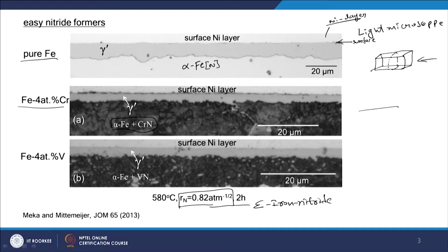You have an alpha iron matrix with the development of chromium nitride precipitates, and now when you do the etching of such a microstructure, because chromium nitride and alpha iron have a very distinct reactivity with your etchant, it creates a large roughness, and that leads to the very dark contrast, like the way pearlite looks when you look in the optical microscope.